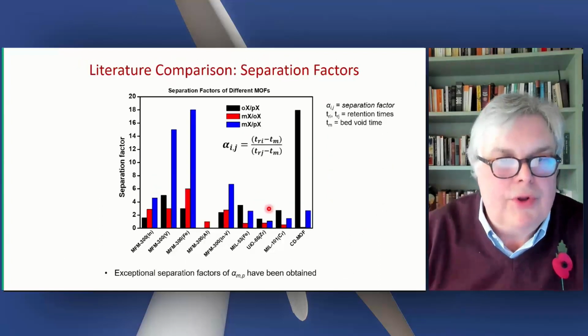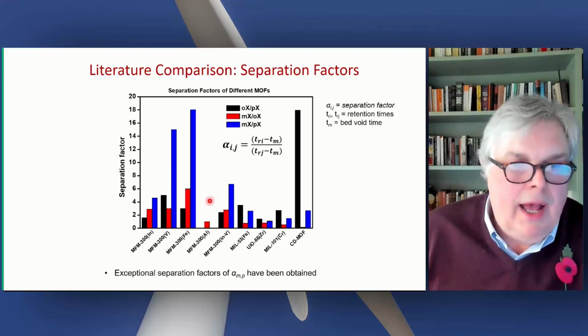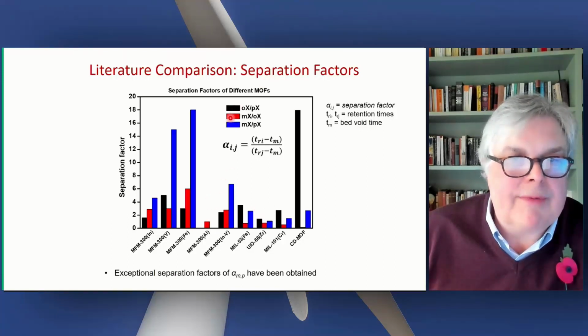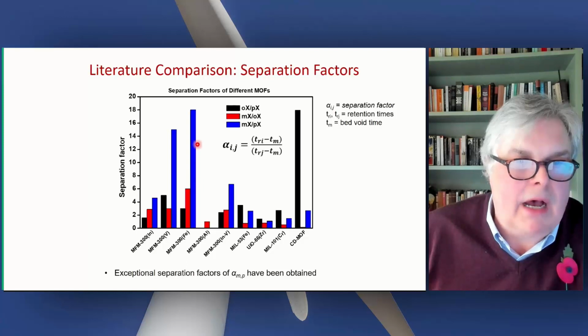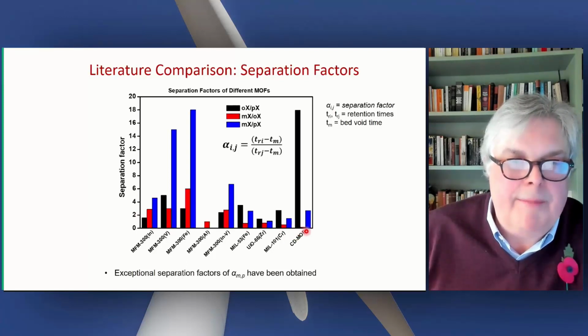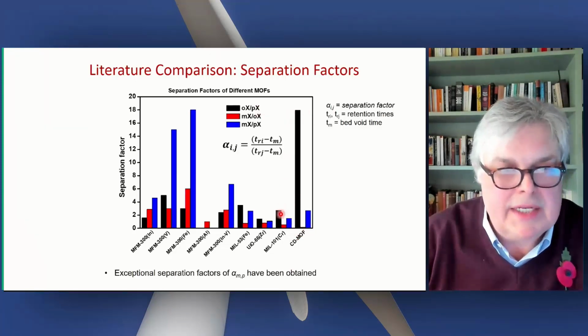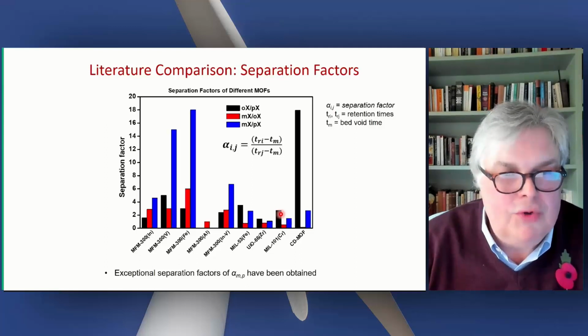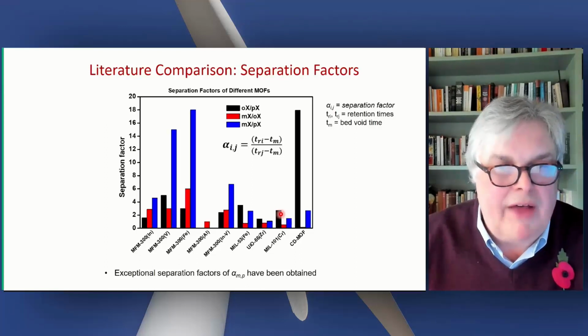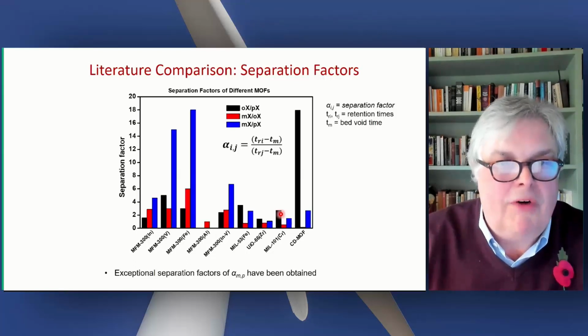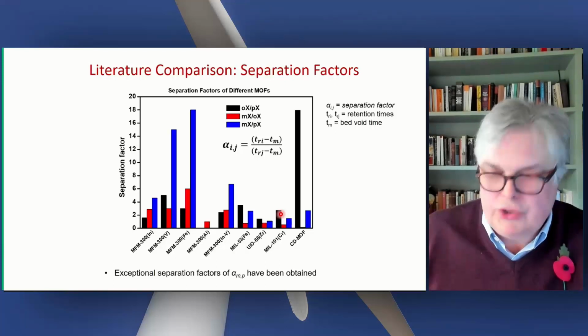And we can look at literature comparisons in terms of the chromatographic separations. In this case, iron is particularly good for meta and para. Vanadium is pretty good. The indium is not so good. And there are some other MOFs that we see here. This is a particular MOF that's good for ortho and para. And that's one of the things I would emphasize. If you vary the MOF, you do vary the selectivity, and it's rather simplistic to say which is the best MOF. It depends on the conditions, the pressure range, the temperature, and precisely what it is you're trying to do.